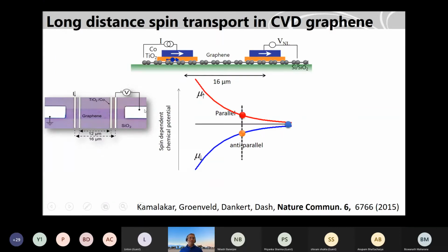What you see here is a graphene stripe. You put this ferromagnetic contact. It's a titanium oxide, 1 nanometer, that just acts as a tunnel barrier. And then there is cobalt, around 50 nanometers, to inject spins. These are done by electron beam lithography, because the contact size should be very small. You want to make it a single domain so that you inject only one type of spin.